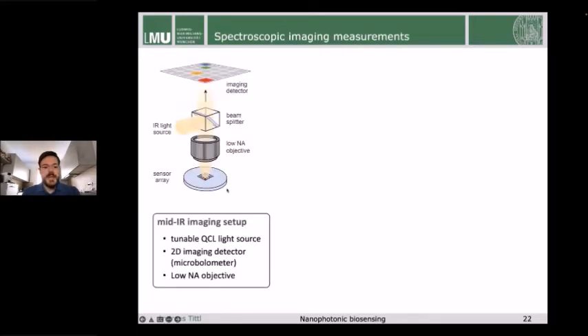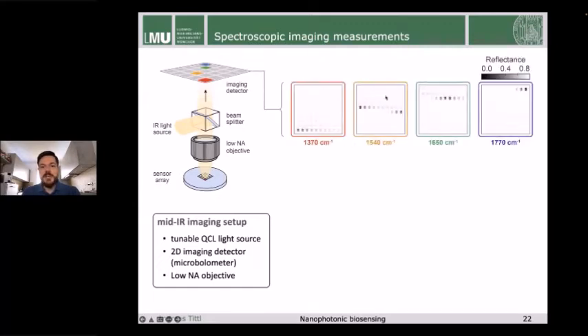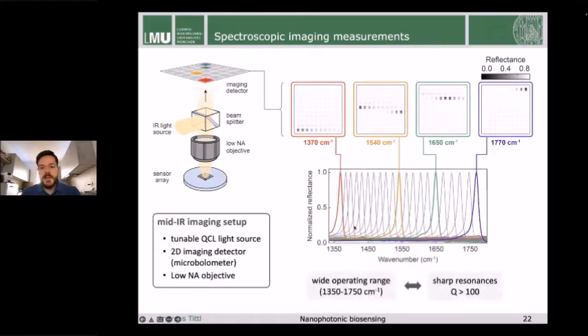Now, to measure it, we use a mid-infrared imaging setup that can capture images of this fabricated metasurface at different wave numbers. And you can see that for the specific wave numbers, you get a reflectance signal only from those pixels that are designed to be resonant at these wavelengths. So you see everything is working nicely. We see this linear scaling over the different wave numbers. And we can use this data also to retrieve the full spectra of these metasurface pixels.